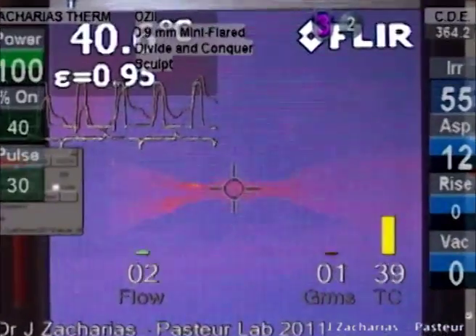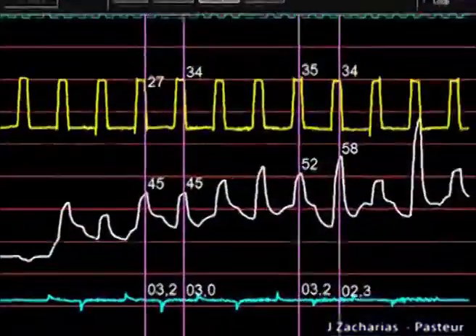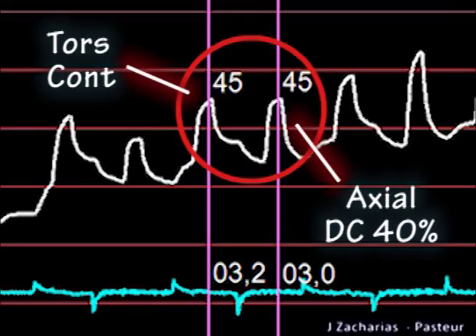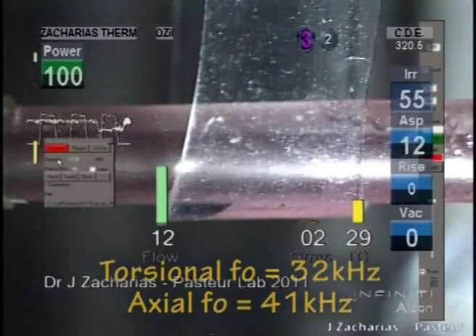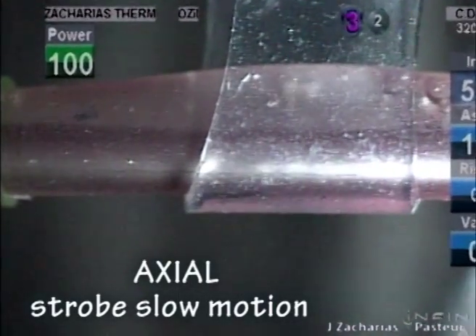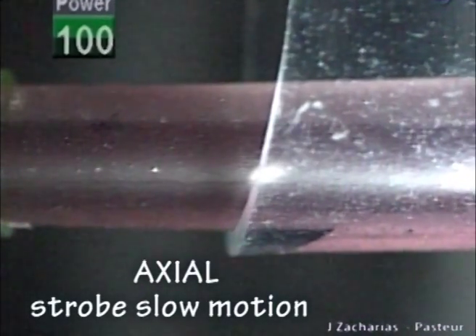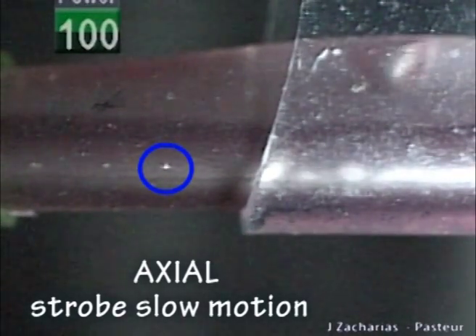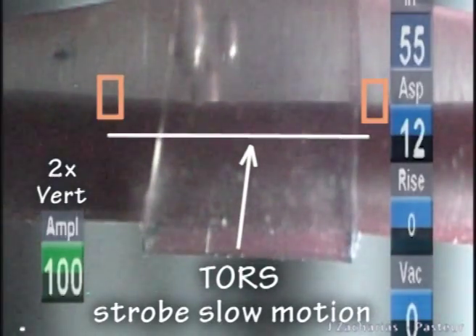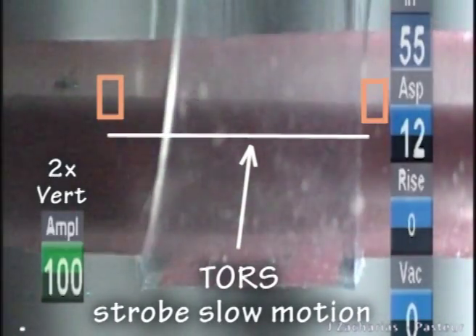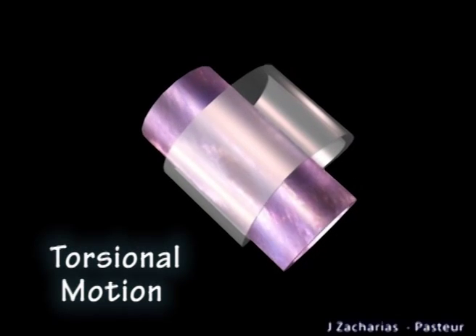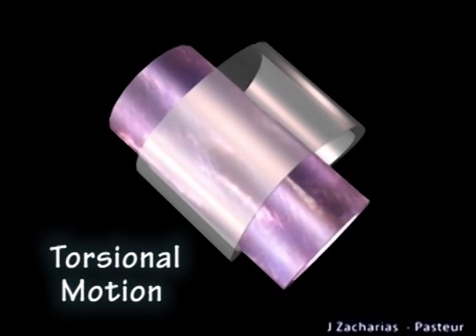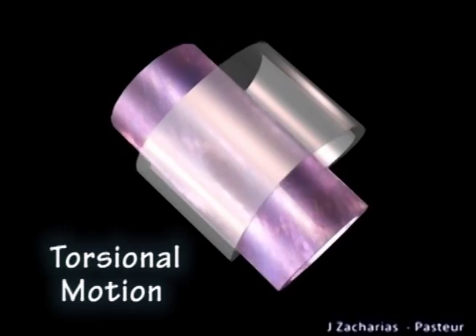Axial power with a duty cycle ranging between 35 and 50% was found to produce temperatures comparable to those of continuous torsional. Besides the lower frequency, to explain these findings, we analyzed probe vibration in the zone of loading. Axial showed a simple back and forth displacement rubbing the sleeve. Torsional showed an undulating movement of the shaft with side-to-side displacements added to rotation. We speculate that the complex nature of the motion pattern with torsional could produce less friction and heat.